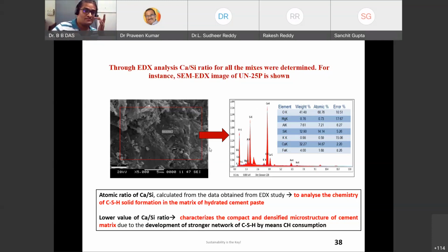Now, how did we do it? You must have seen this image, and I have to define a boundary when I integrate EDX. From this boundary I am getting these peaks. These peaks are the elemental peaks, and this table gives me the quantification of the elements. You can see calcium 32.27, silica 12.9. Oxygen, magnesium, everything is there, but for me, what is important is calcium divided by silica.